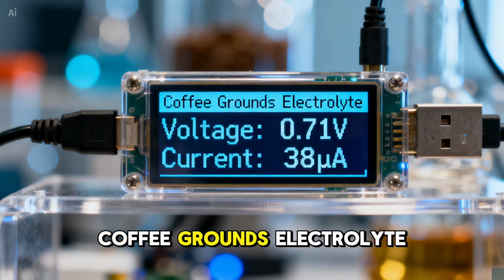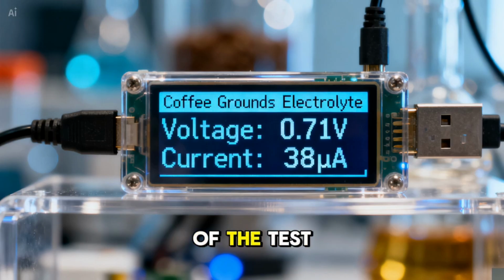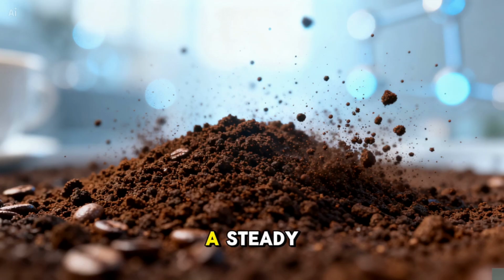Coffee grounds electrolyte. At the start of the test, it produced 0.71 volts and 38 microamps. After 24 hours, it dropped to 0.53 volts and 22 microamps. After 72 hours, 0.31 volts and 11 microamps. A steady, consistent decline as the organic acids broke down and the ion concentration dropped.